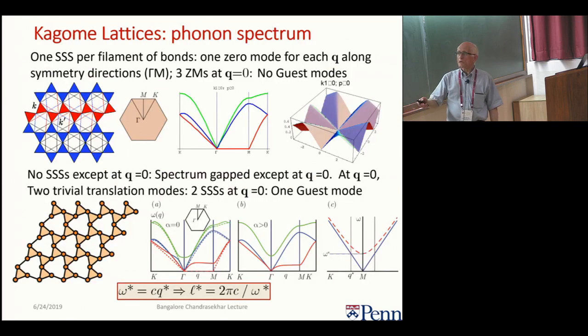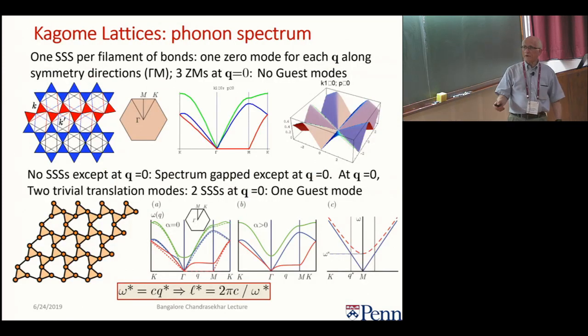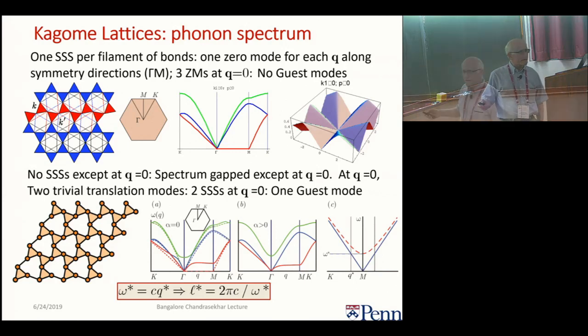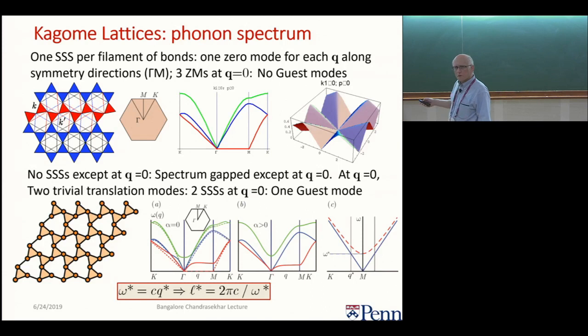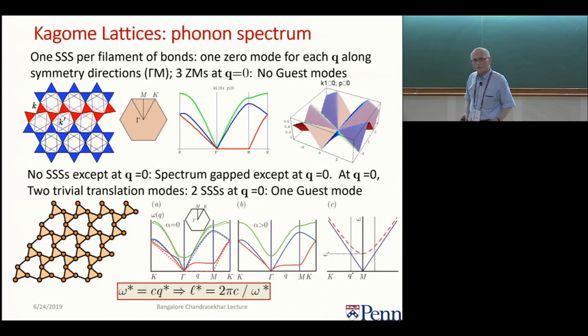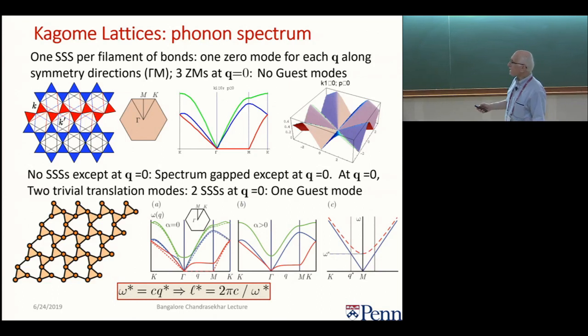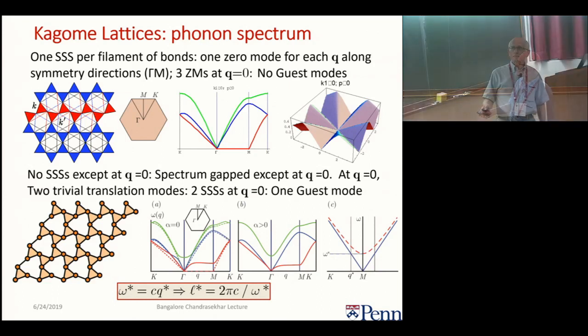Now, if you live in a physics department, I think it's pretty hard to avoid seeing something like this at some time in your life. This is exactly what happens in polyacetylene. It's exactly what happens in topological insulators. You have a gap that forms. Once the gap forms, that means that you can't change the bulk properties of the system if you just have slow variations away from the state that has that gap. So there's a finite region of parameter space where the gap is there, and you have the properties associated with it. And that's why we say that the states that arise from this are topologically protected. And so what we're going to find in a moment is that the Kagome lattice with the straight lines of bonds, states of self-stress, is a transition lattice between one type of topological lattice and another one.